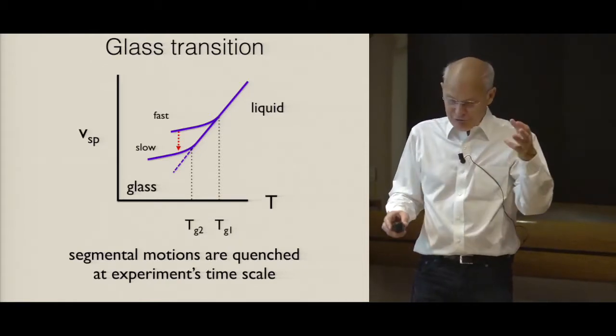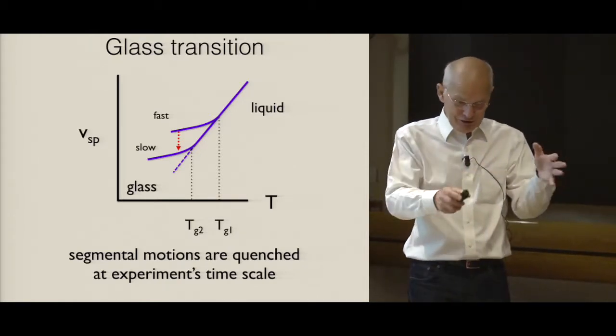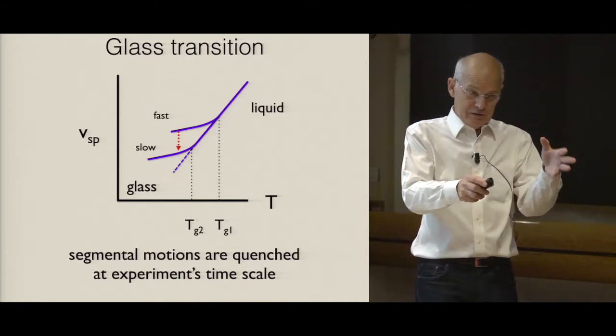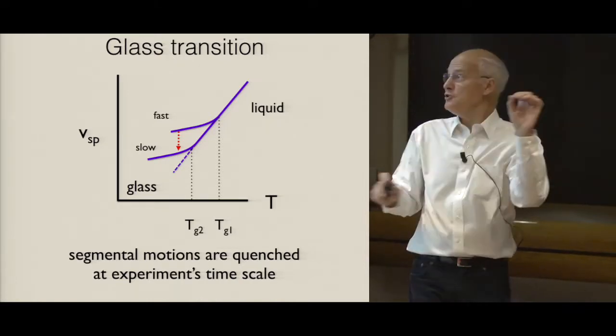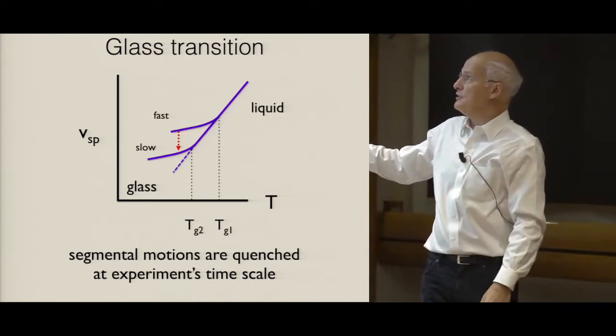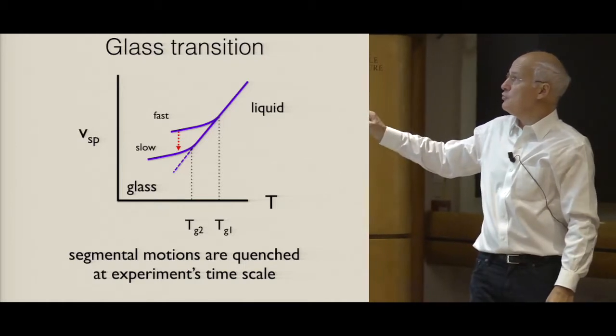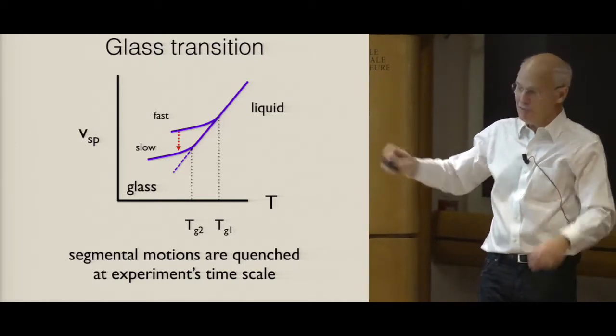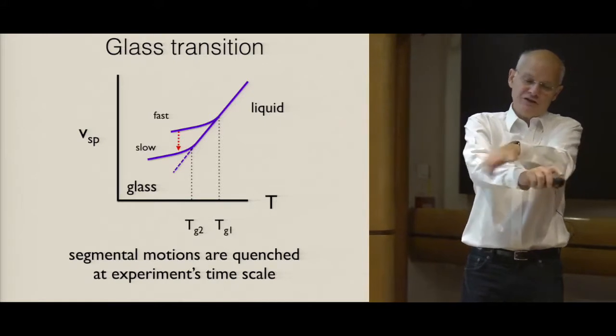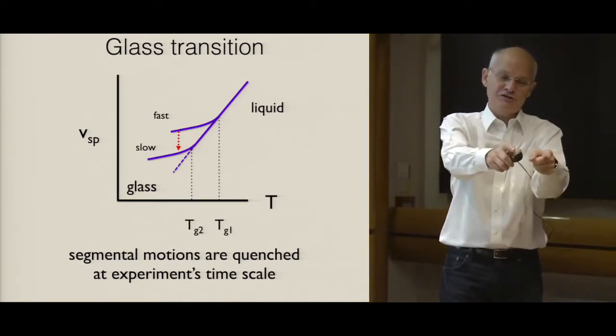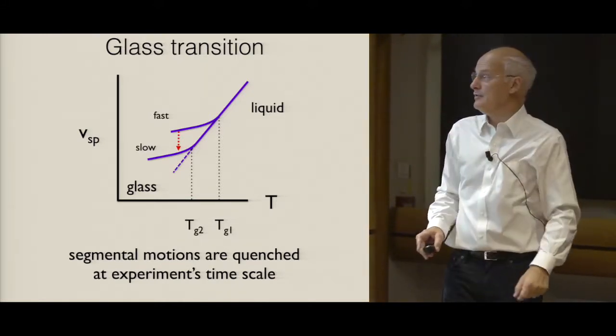And so with polystyrene, what you really quench are the local motions of the polymers, because you change a little bit the density of the system. So when you cool, the density increases, there is less free volume, and you basically quench the motions on some semi-local scale.